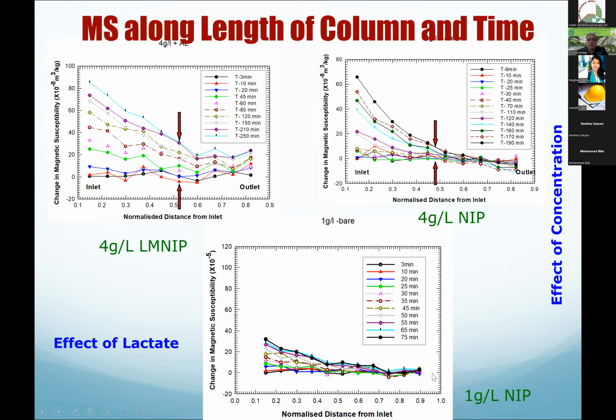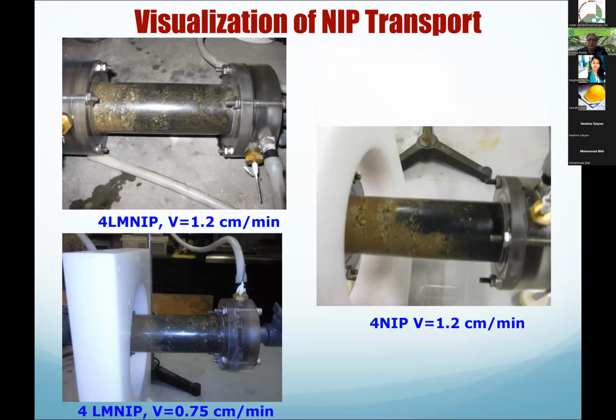This is for 1 gram per liter NIP. Again, with the 4 gram per liter and 1 gram per liter, there's not much change in the magnetic susceptibility, but it clearly shows that if you have lactate modified nanoiron particles, these particles are moving through the sand very nicely. So this is kind of a small visualization with pictures.